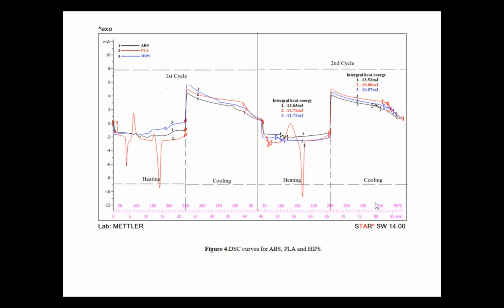Then we also try to see their thermal stability. Like you see, from room temperature to 250, from 250 to room temperature, then from room temperature to 250, and then again to room temperature. So different heating and cooling cycles. Normally it is recommended that we must see a minimum of 3 cycles to establish this, right? So we see how much energy it is absorbing. Like for ABS, it is absorbing 13.63 in heating, and it is releasing 13.52. So that means the material is thermally stable. Whereas for PLA it is absorbing 14.71 and releasing 10.80. That means there is a problem with the thermal stability of this material.